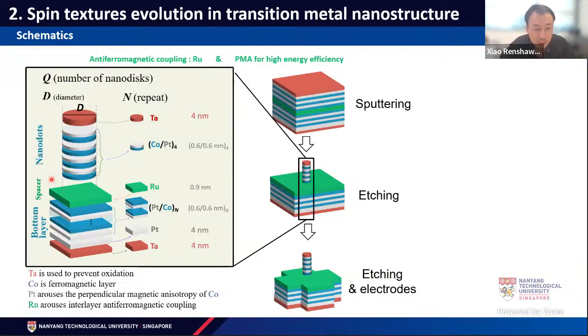So we grow these multilayers using sputtering, and then we first etch the top multilayers into a nanodot, of course patterned by E-beam lithography. Then for the bottom layer, we also use etching, and then we contact with the electrode. So eventually we have electrical contact on the sample.